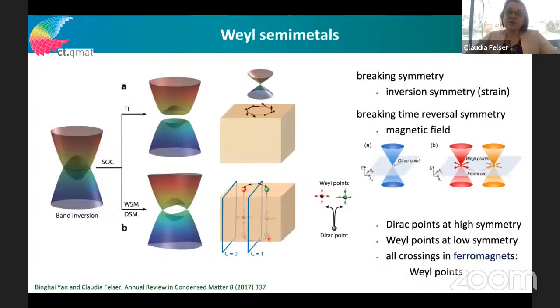So I simply want to explain what is the origin of this crossing point. As I explained before, we can have a material with a valence band and a conduction band, and in the semimetal we can have this overlapping region. This region is a nodal line here, for example, and depending on the symmetry of the bands and the symmetry of our crystal, if we apply spin-orbit coupling, so spin is not a good quantum number, this can become a forbidden crossing and open up a band gap, and we get a topological insulator. So this is a 3-dimensional version of the electronic structure I have shown you before.